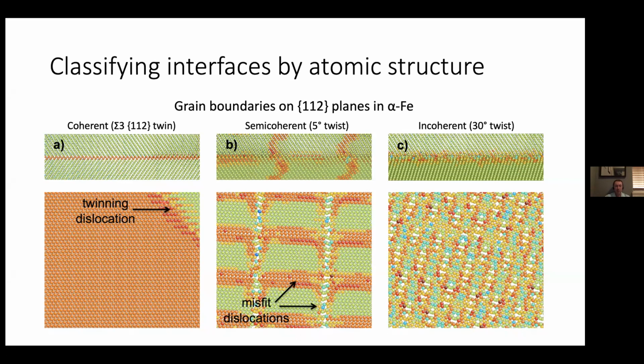I was lucky enough in this particular model to catch a twinning dislocation. That happened just willy-nilly by itself. It's not intentional, but it sort of is a nice illustration of this kind of defect that can form at a coherent twin boundary.